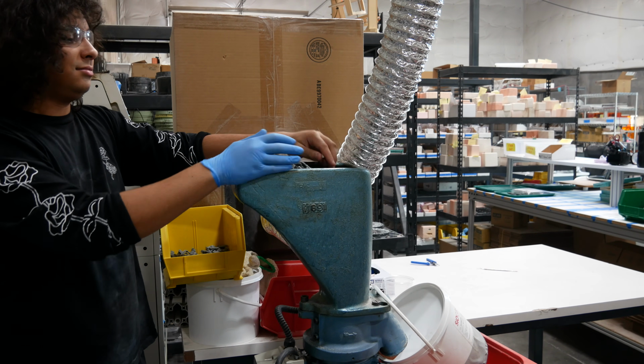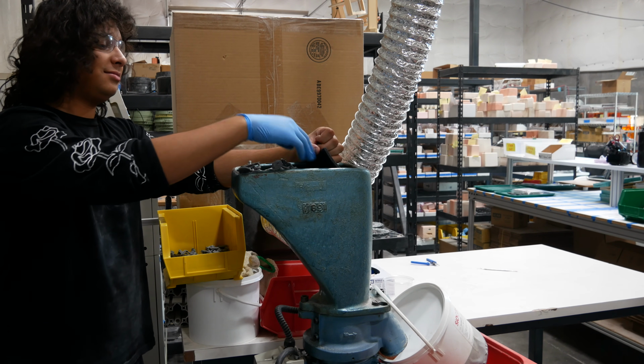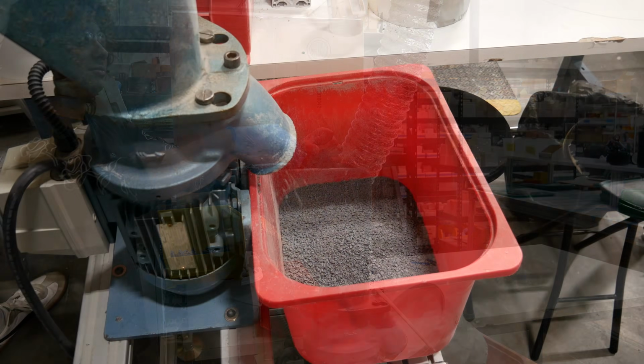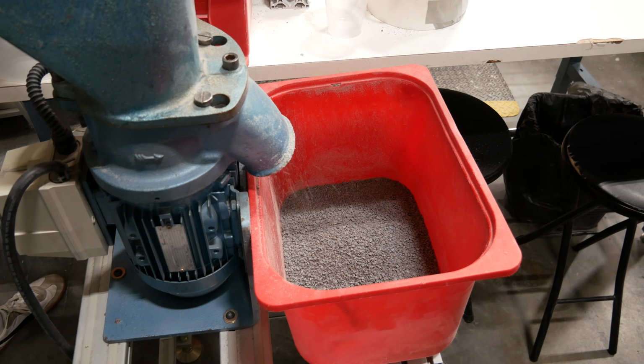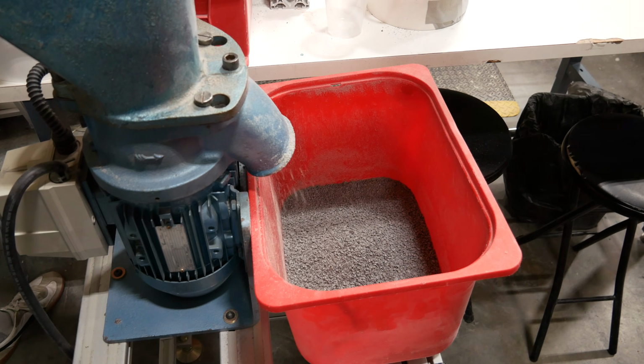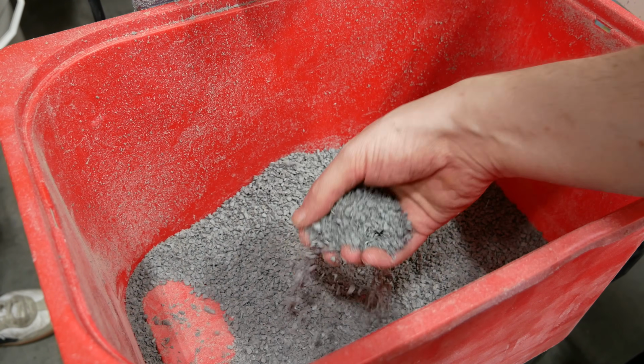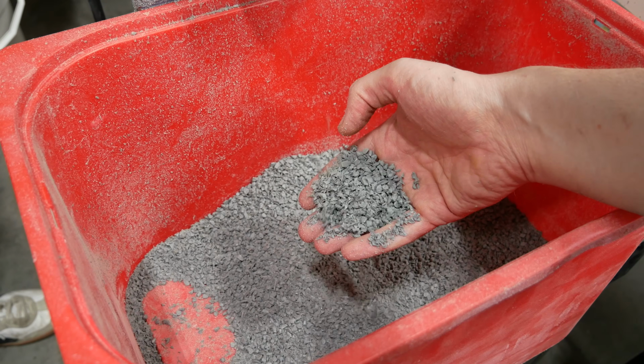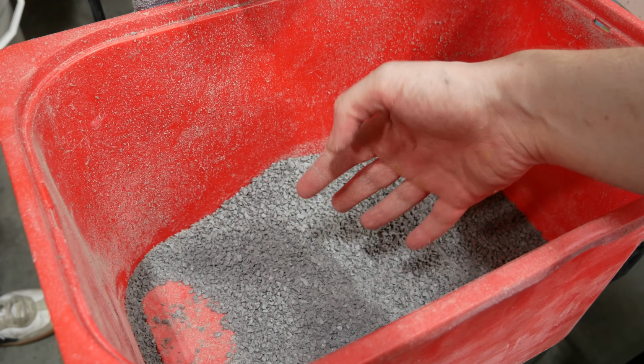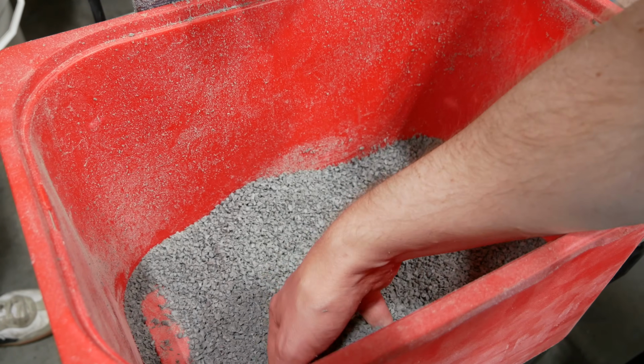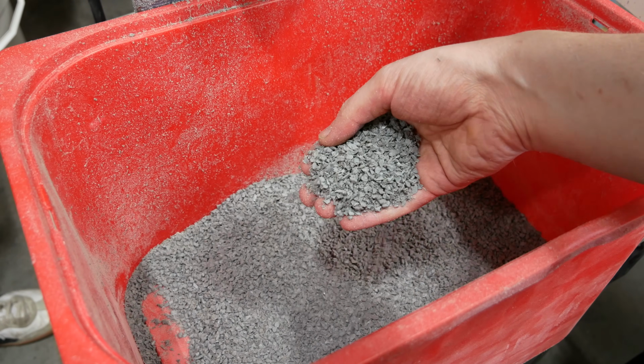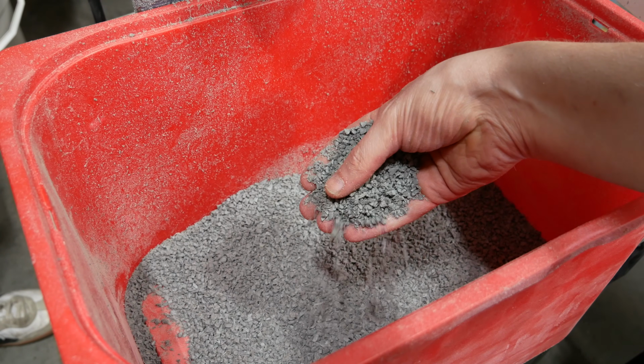Thermoplastic can be recycled. The sprues and miscast minis are put into a grinder. They get ground up into these flakes, and they can be poured back into the instrument to be melted down and used again. The plastic can degrade after a few melting cycles, so it's not infinitely recyclable in the way that pewter is. The waste from the factory is generally mixed with new pellets and reused.